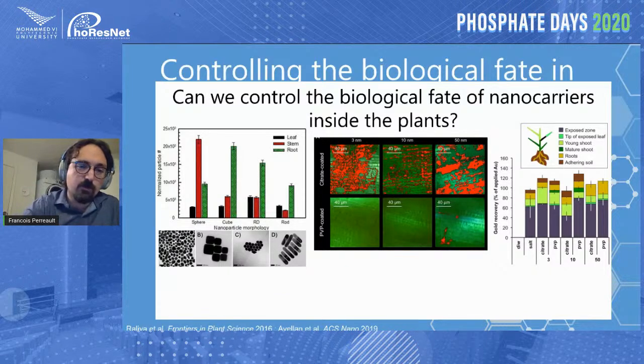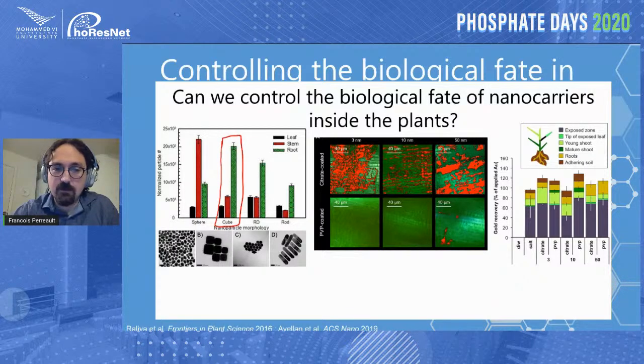For example, if you use a cubic particle, you can enrich the root system compared to the leaf. And this is all for foliar application. The particle relocates from the leaf to the roots, and changing the morphology of the particle can really guide where it is going. Similarly, you can do the same thing if you change the surface chemistry or the size.